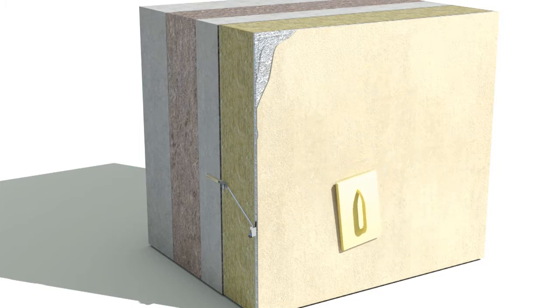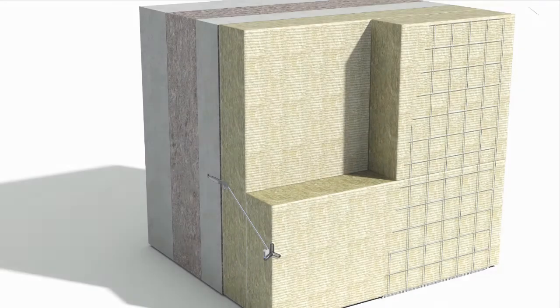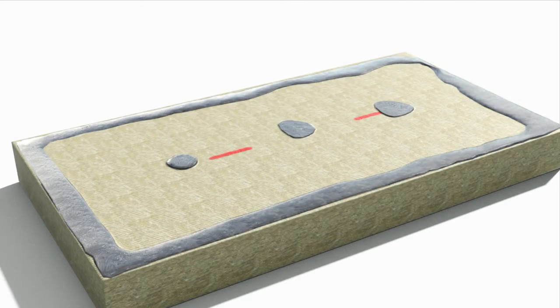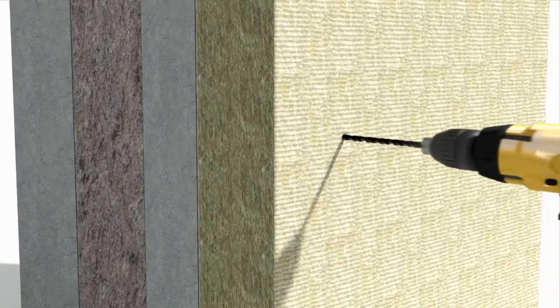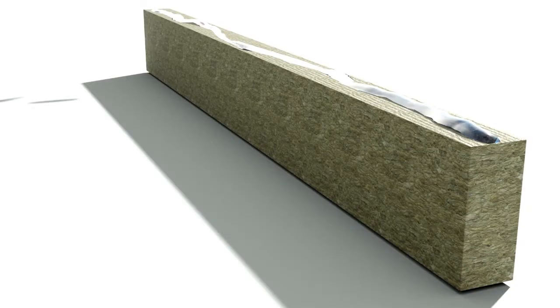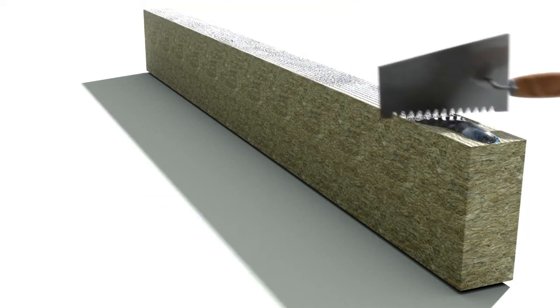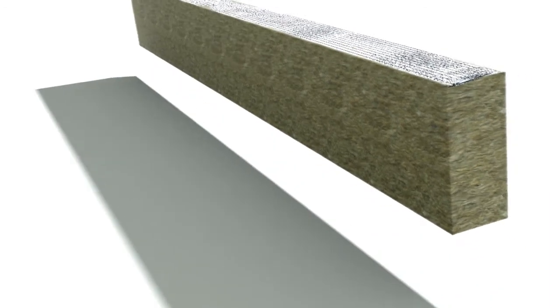If the building is designed to meet passive house requirements, or if the thermal insulation layer otherwise is thick, it's recommended that the thermal insulation is executed in two different layers with overlapping slab seams. If a thin insulation render structure is specified for the building, use thermal insulation PAROC FAS 4 in case a slab product is required, or in case a lamella product is required, use PAROC FAL 1, which can be fixed to the substructure by adhesive mortar only. The lamella product can always be mounted in one layer, however thick the insulation layer is.